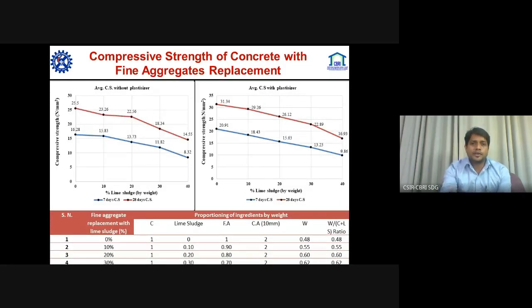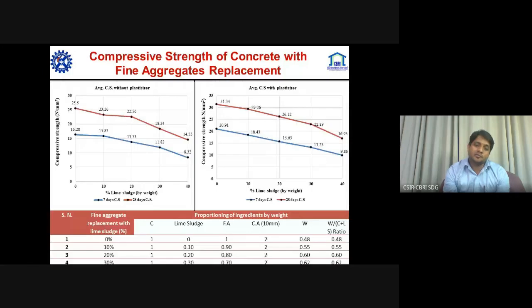We also did it with fine aggregate replacement, and it was seen that without plasticizer we could replace the fine aggregates with lime sludge up to 20%, but with plasticizer it was increased up to almost 30%. So when we are replacing fine aggregate with lime sludge, we can use plasticizer, but when we are replacing cement with lime sludge, we have to use a highly reactive pozzolanic material, which can be nanosilica.